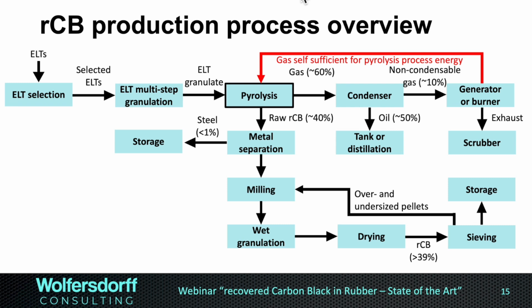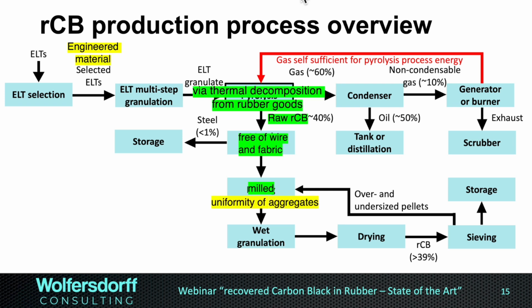Then on the recovered carbon black side, metal separation, we need the milling. Then we would go into wet granulation, just like furnace carbon black. We go into drying, which is actually one of the big cost factors in the whole process, to dry off the water from the 50% moisture containing wet pellet. Then we go into sieving and storage, and of course over and undersized pellets need to go back to milling. Interestingly, the keywords engineered materials really for me start at selecting the end-of-life tires. We have the thermal decomposition, we have raw recovered carbon black, free of wire and fabric. The fabric typically is decomposed in the pyrolysis. Then we need to mill for the uniformity of aggregates. This is not the primary particles uniformity, but the uniformity of the particles of the raw recovered carbon black.